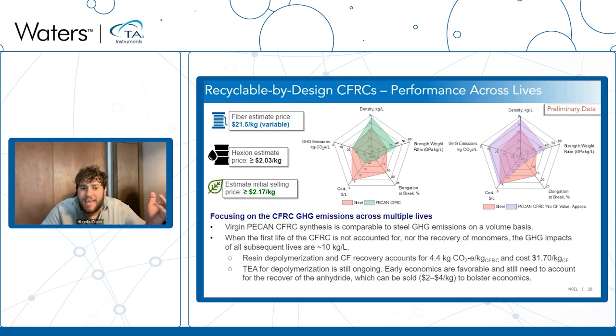So the last thing I want to shout out here is that we can also make our resins near cost competitive with today's petrochemical epoxy amine resins. Once again, you see a spider chart. On this middle figure is a spider chart for the first life of this material. And you see that we have low density, high strength-to-weight ratio materials and low elongation at break. However, since our materials use carbon fiber, which is really energy intensive, on the first life their GHG emissions are comparable with steel and their cost is a lot higher than steel on a volumetric basis.